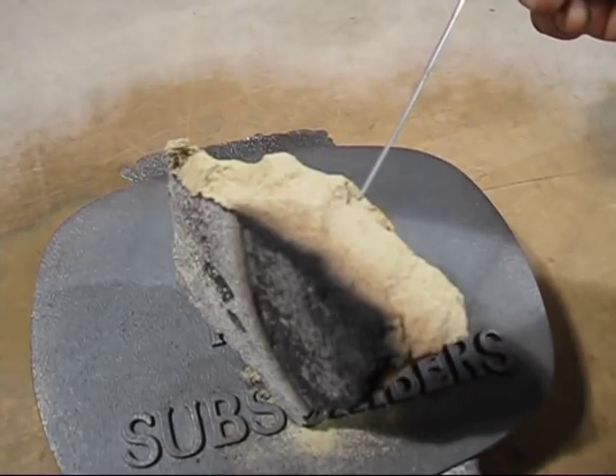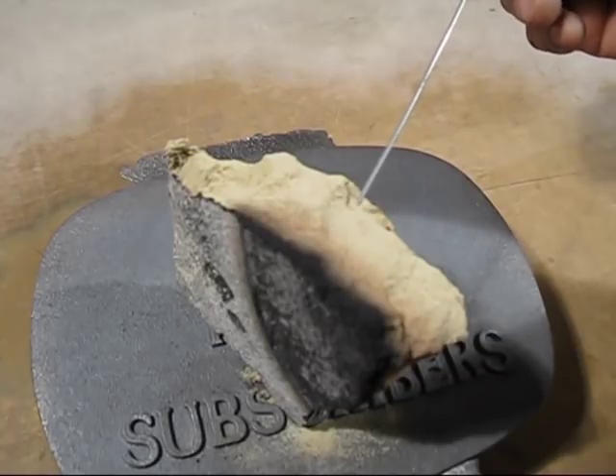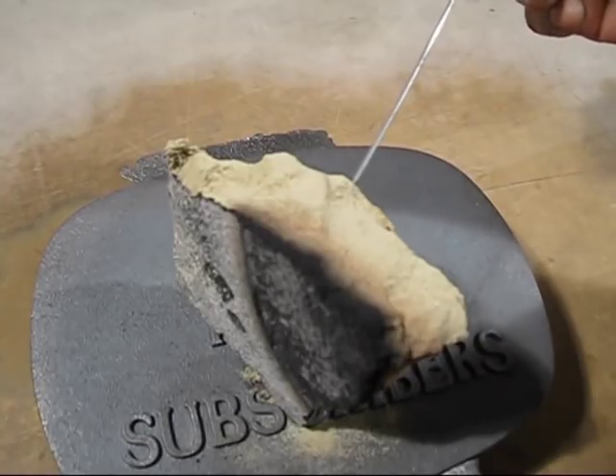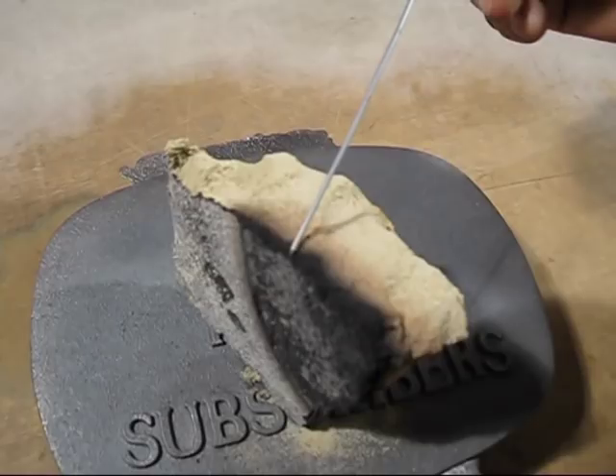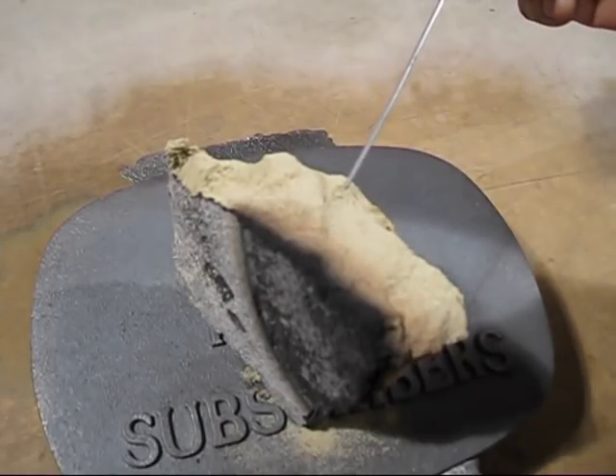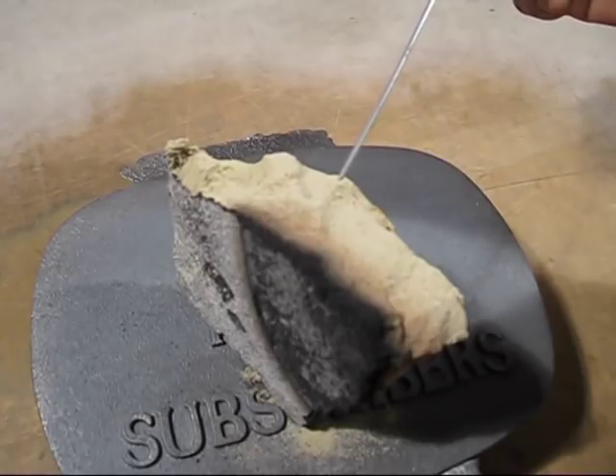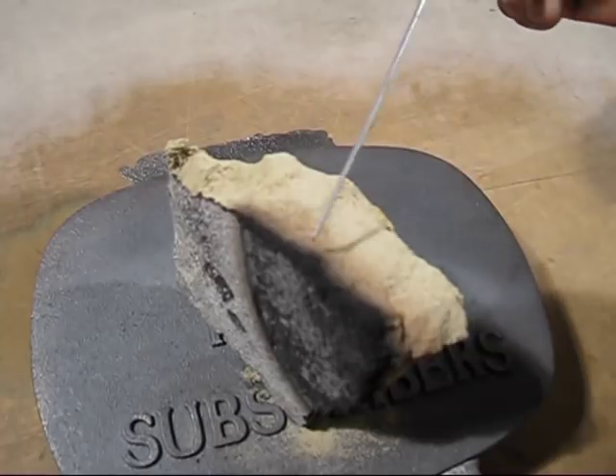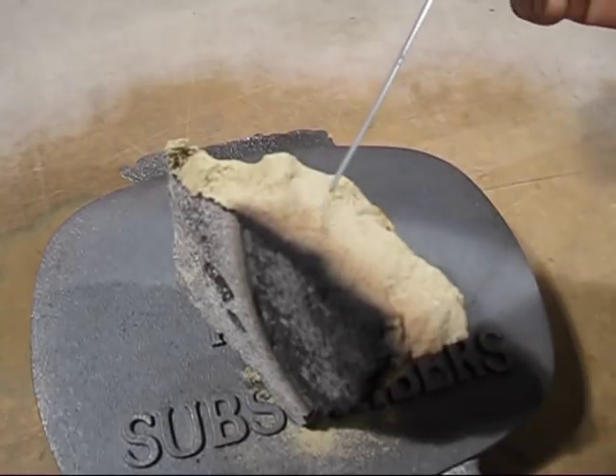So you can ask, why haven't I got coal dust over here? Well, coal dust over here has no use because it's too far away from the edge of the mould, and also over time coal dust destroys the bond in sand, so you have to keep adding bentonite to it. And if you put facing sand on, this sand lasts a lot longer.